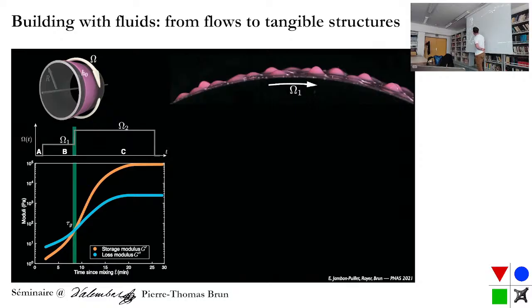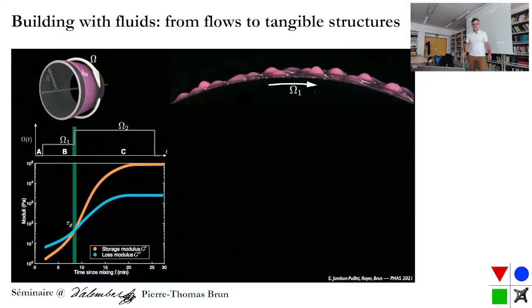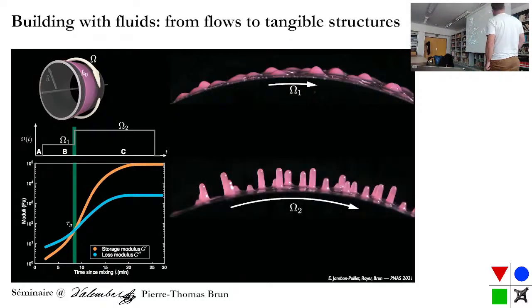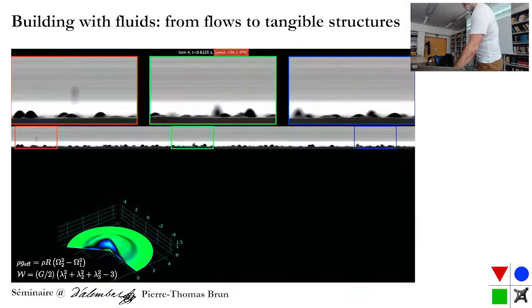But the cross-linking continues, and eventually you get something which is an elastic material all the same. So first, when we increase, it's already a gooey substance, so it's not going to flow and make other droplets. It's actually going to stretch and create these hair-like structures. And what else? Well, nothing, right? So really, because you create a new reference frame, or shape, which will cure. And so when you go back to zero, these guys, they stay, right? So you grow, you stretch them, they cure, you relax the speeds, and then they just stay the same. Okay, and so we want to understand how they're formed.